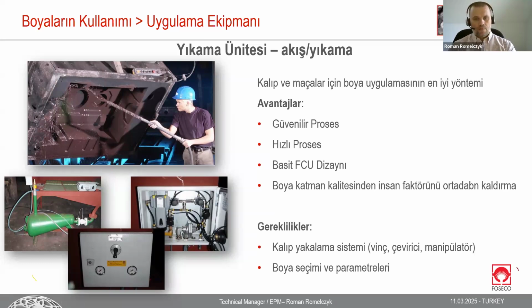So for that kind of application method, it's specially designed recipes with long flow to give us a chance to have a layer thickness without drops, tears, and a constant level of layer over the whole mold. The difference between the top part of the mold, visible in the picture, and the bottom part, if everything is prepared correctly, will of course exist, but usually it's some 50 microns, sometimes 100 microns. It depends on the size of the mold.